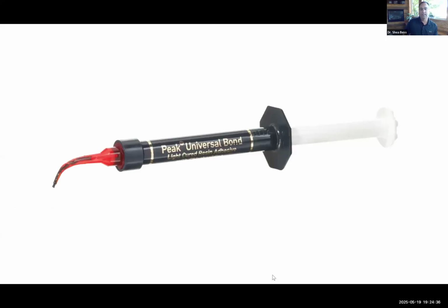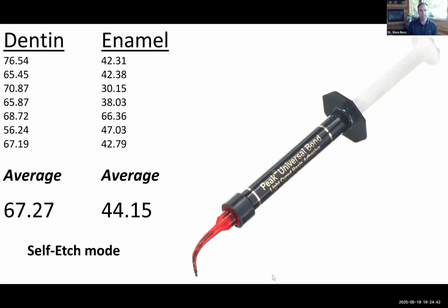So this is Peak Universal Bond, and this is the adhesive that Ultradent makes. And so I took 7 specimens of dentin and 7 specimens of enamel, and this is in their self-etch. So with Peak Universal Bond, you can use it in one of 2 ways. You can use it as a self-etch adhesive, or you can use it as a total etch adhesive. And so I tested it both ways. And this is the highest average bond strength to dentin using any adhesive out there that I found in self-etch mode. So I used their self-etch product, their self-etch acid, to etch the tooth, and then blew that off, and then applied the adhesive on,